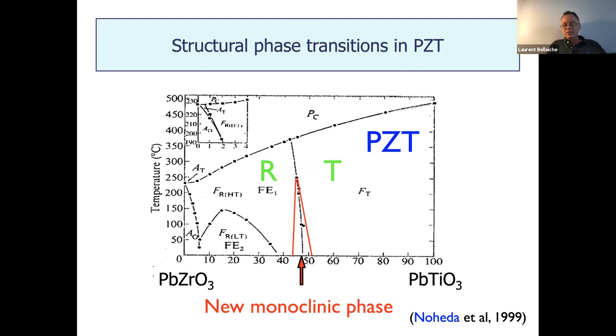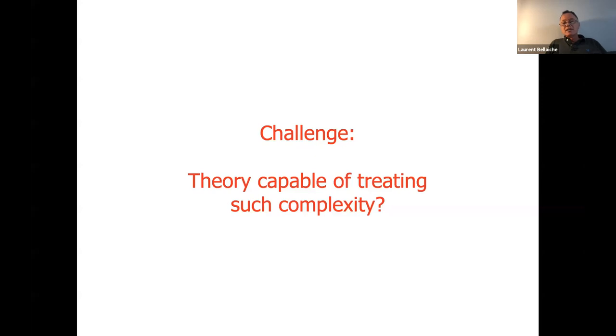You go from lead zirconate on the left to lead titanate on the right. Beatriz Noheda and collaborators in 1999 found that in addition to the rhombohedral state for lead zirconate rich systems and the tetragonal state for titanium rich systems, there is a tiny compositional area for which it's neither rhombohedral nor tetragonal. It is a monoclinic phase. It was a nice discovery because PZT had been known for some time, but the monoclinic phase was discovered 20 years ago. So the challenge is as follows.